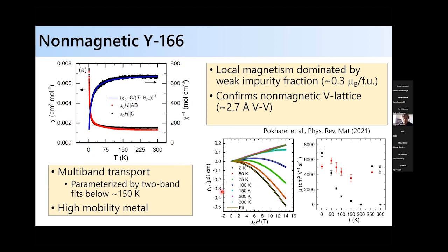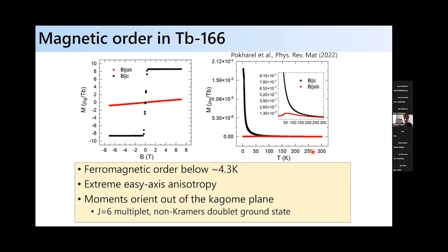If you look at these compounds, you can parameterize the Hall response via a two-band model, and they're reasonably high mobility metals. And this picture more or less holds for all of the variants I'll be showing you. But what we can do is take the yttrium ion out and replace it with a magnetic ion. The first one we chose is one that you typically expect to add some strong anisotropy to the system. So we put terbium. So it's terbium vanadium 6 tin 6.